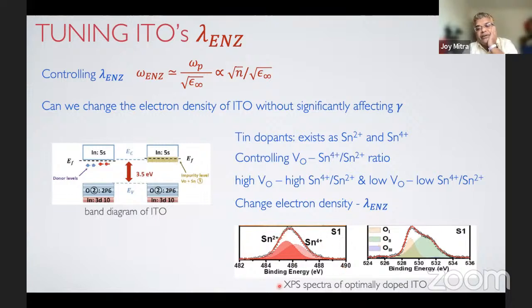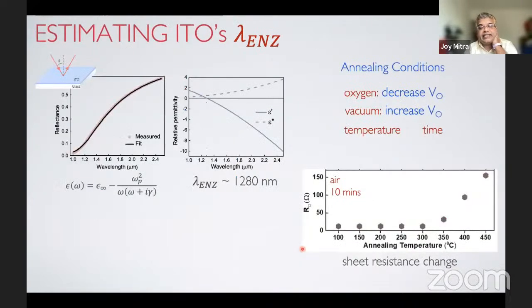Okay. So once we realized this, we started looking very carefully at the tin ratio with XPS spectroscopy of an optimally doped indium tin oxide. Here, the first graph gives you the peaks for Sn2+ and Sn4+, and then an oxygen peak here and another oxygen peak here. These two oxygen peaks originate from very different sources. This is oxygen in a stoichiometrically pure region, whereas this is oxygen in an oxygen deficient region. So if I tune the ratio of these two peaks, notionally what we expected was that these two will also change. And let's see if that happened.